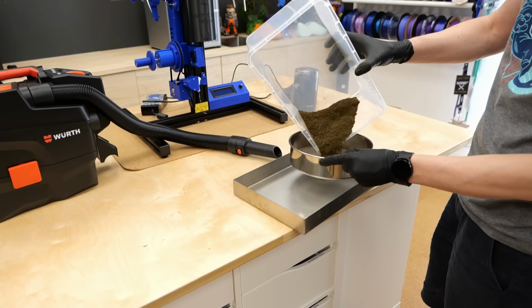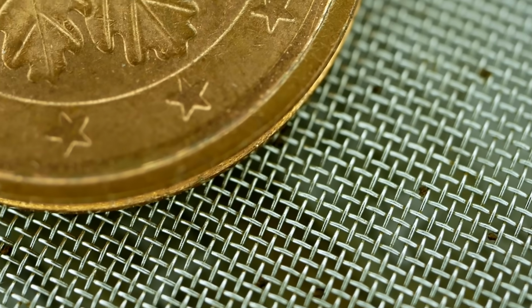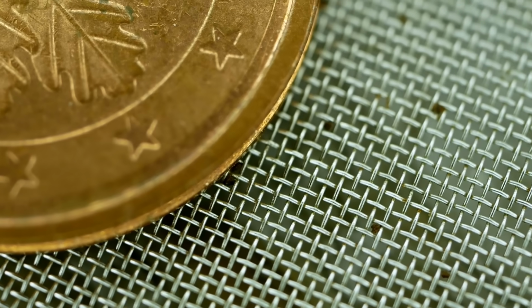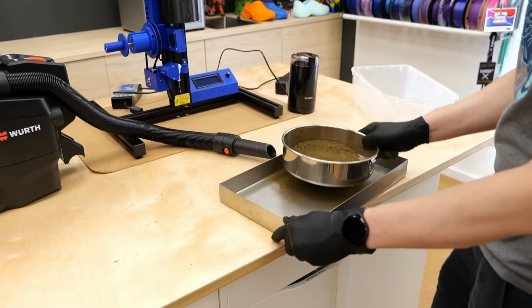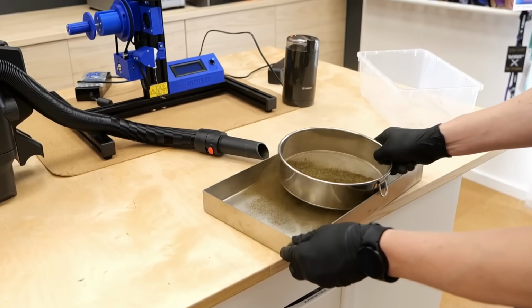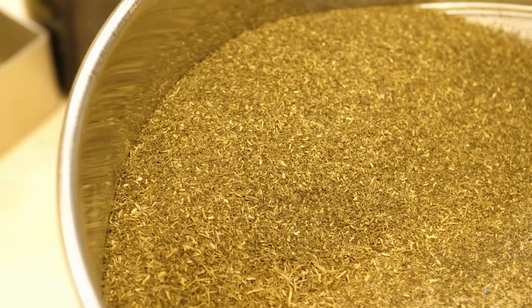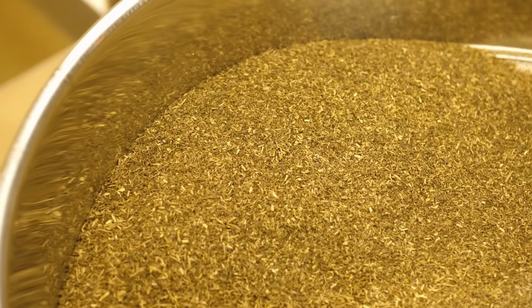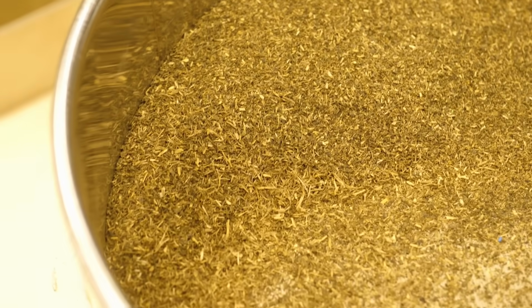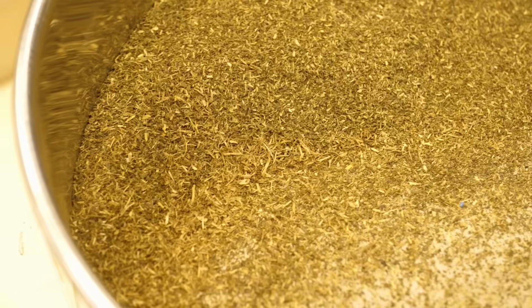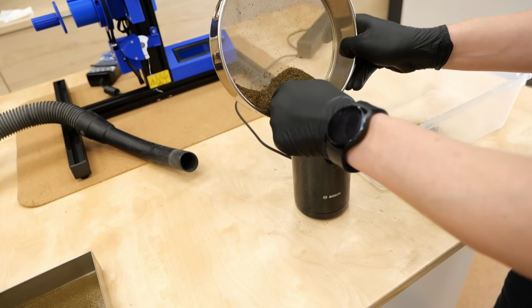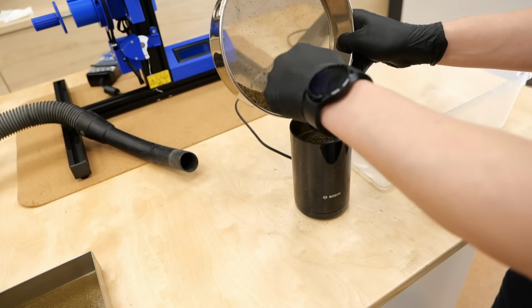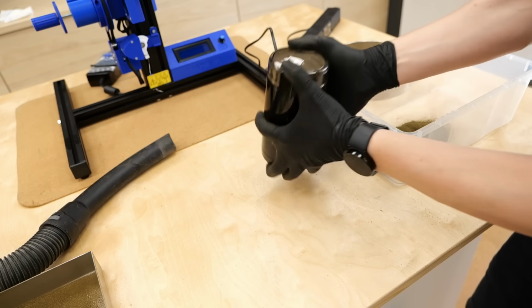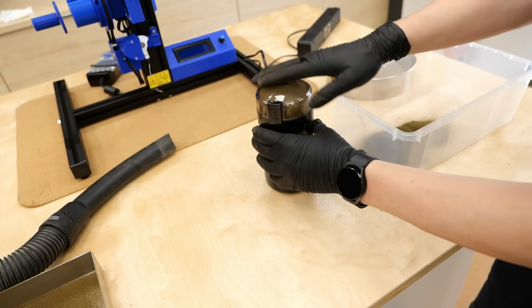In my case, I used a 60 mesh sieve, which has an opening size of 0.25 millimeters. That's still on the bigger side for such small nozzles, but it was the only thing I had at that point. And by looking at the amount of material that stayed in the sieve, it was obvious that a lot of the material didn't meet the size criterion. So I took that, put it back into the coffee grinder and blended it another time to get a bit more material out until I thought I had enough for a first run.